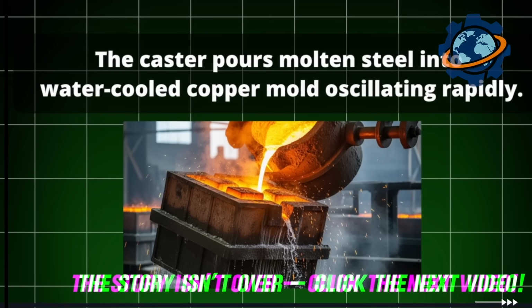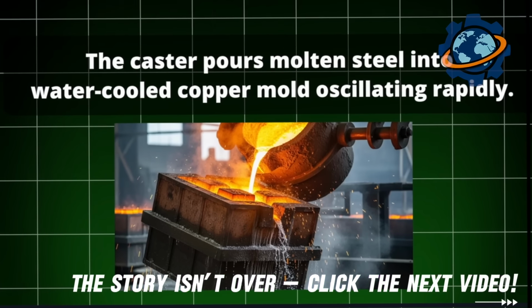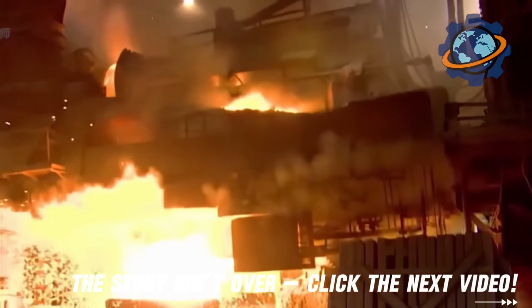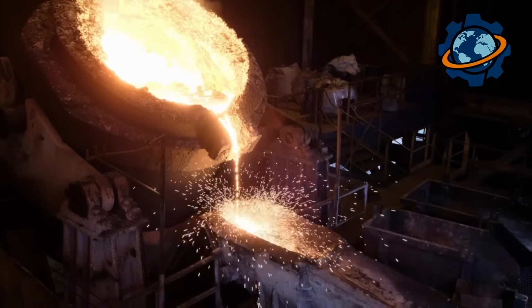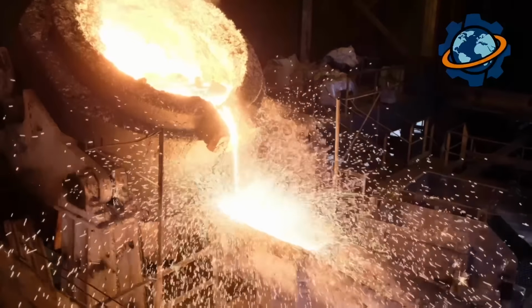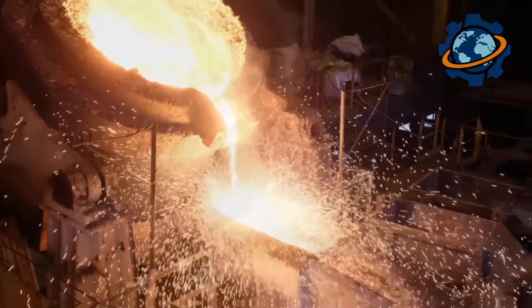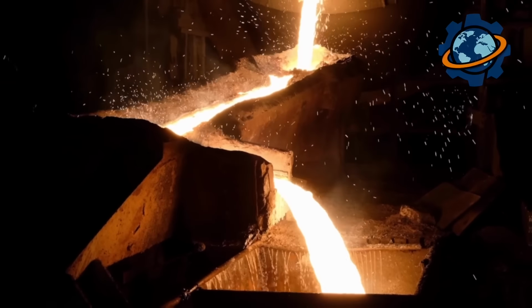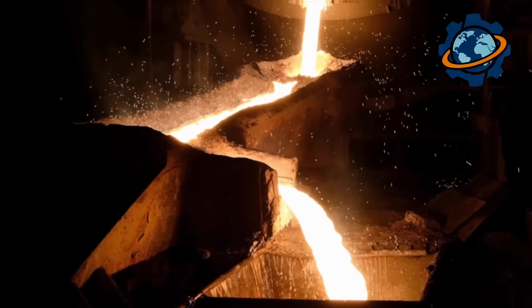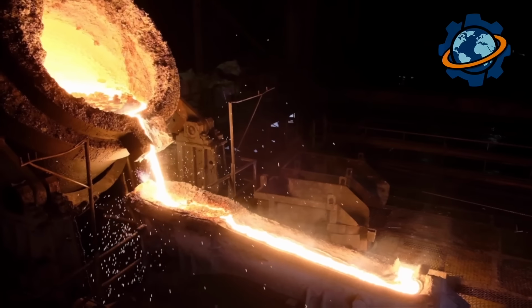The caster pours molten steel into a water-cooled copper mold, oscillating rapidly. As steel contacts the mold, the outer shell solidifies while the interior remains liquid. The strand, a continuous ribbon of solid steel, emerges from the bottom, bent gradually from vertical to horizontal through a roller system. Torches cut the continuous strand into billets 20 feet long, each weighing 4 tons.